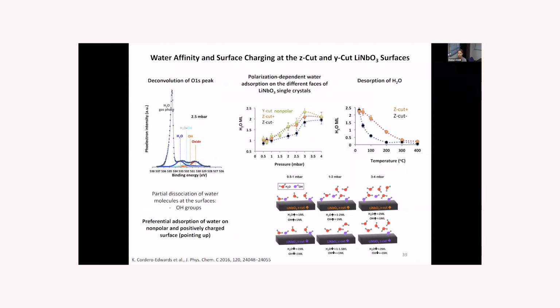Before me working with Albert, he was already working on this kind of polar surfaces, and they studied by ambient pressure XPS the water affinity of surface charging at the different cuts of lithium niobate. And they have 3 different surfaces: the nonpolar Y cut, Z plus cut, and Z minus cut. And by deconvoluting the oxygen 1s peaks of the XPS, they could see that there is a partial dissociation of water molecules at the surfaces and creation of the hydroxyl groups.